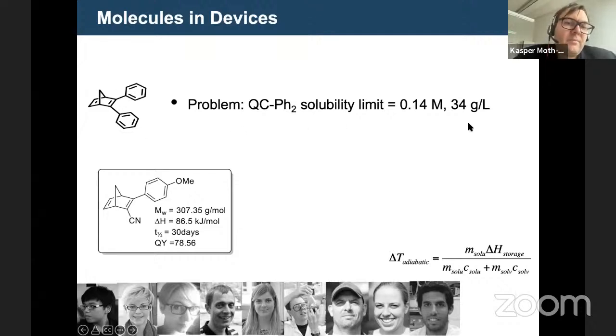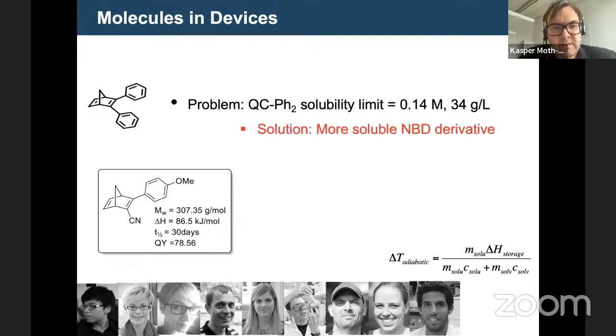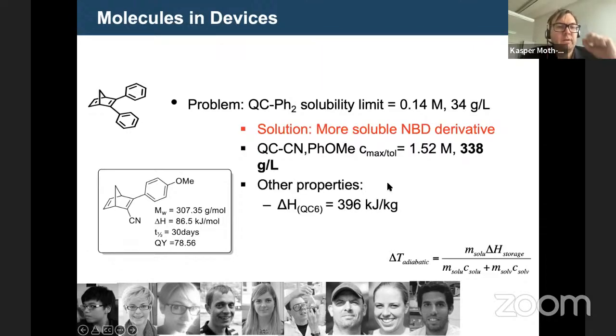So this one had the problem that the solubility of this was only 34 grams per liter. So this means that there will be much more solvent than molecules. So in the next molecule, this one had a much better solubility, up to 300 grams per liter. And with that, we could try to see if we could recover the energy that we could store in the system.